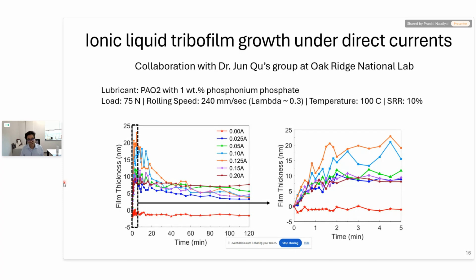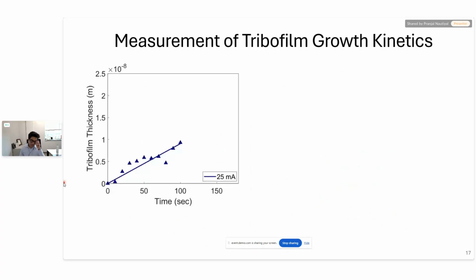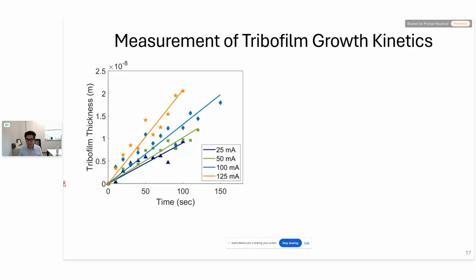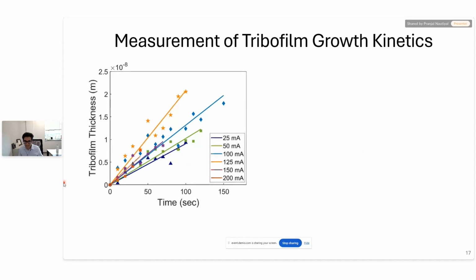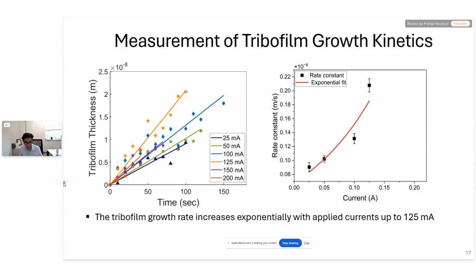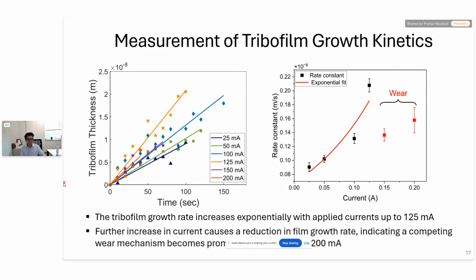We can extract the growth rate of these tribofilms by just doing a linear fit. We just assumed that the growth kinetics of these tribofilms followed zero-order kinetics. So we can do a linear fit and obtain the rate constant as a function of applied current. We saw that up to 125 milliamp, there was an exponential increase in rate constant with applied current. But with further increase in current, the growth was suppressed, and we did not see that exponential increase anymore, which we think happens because of wear activated at these higher currents. I'm going to show those results in a moment.